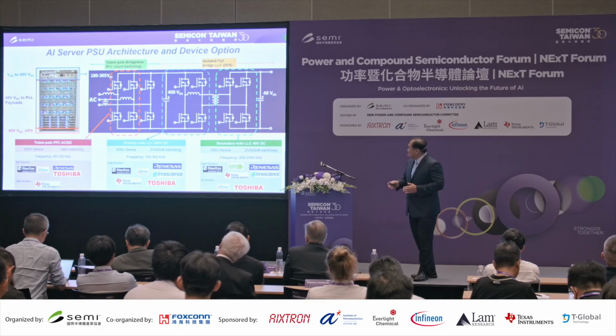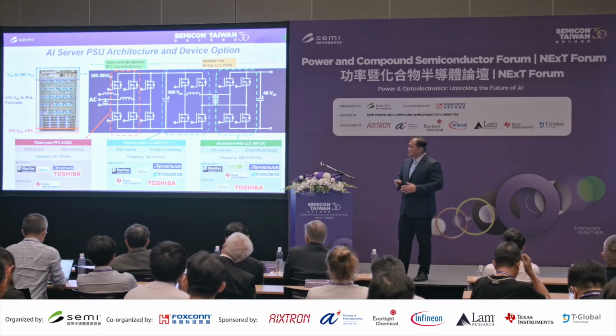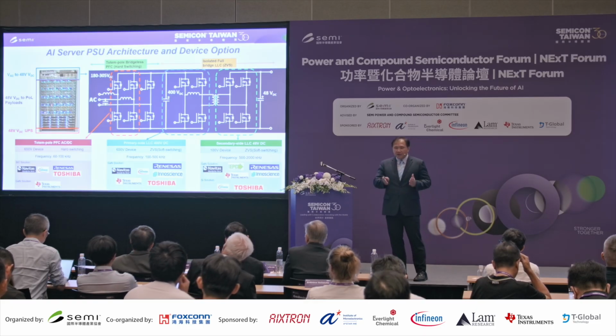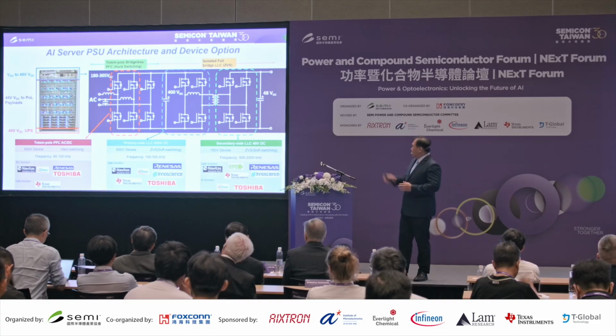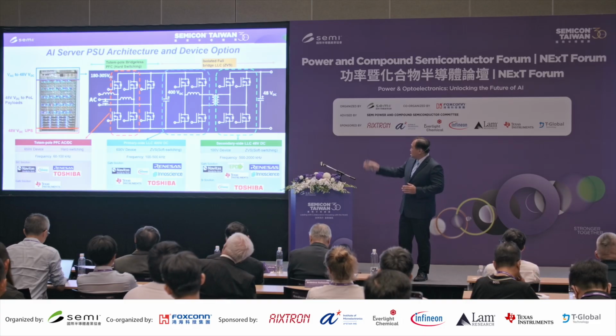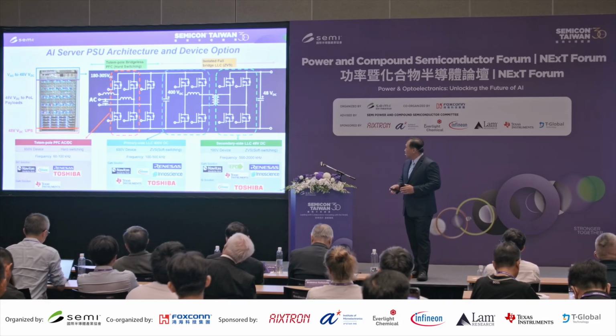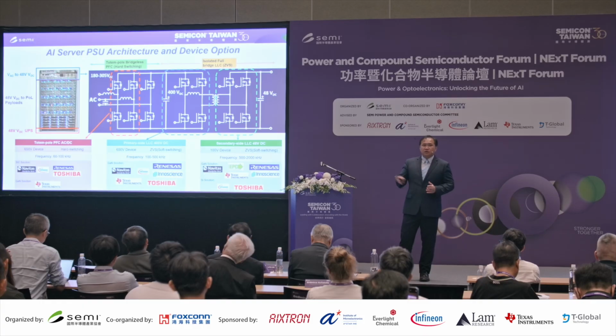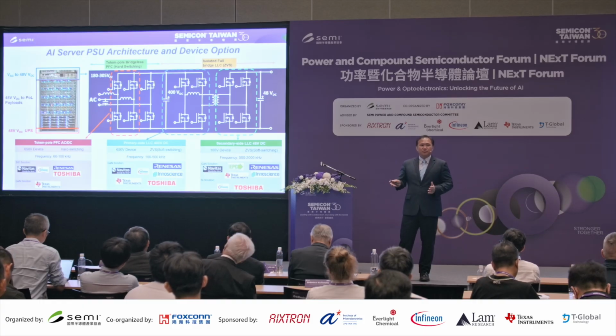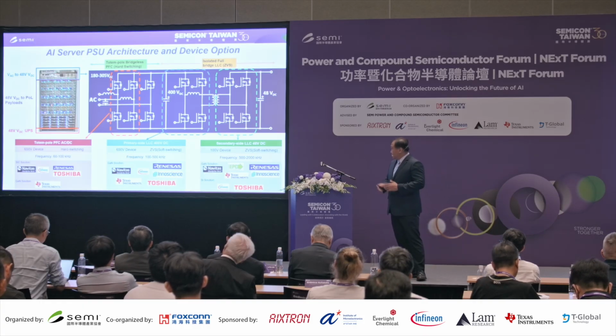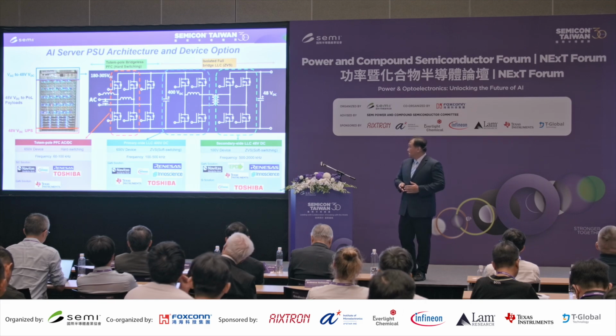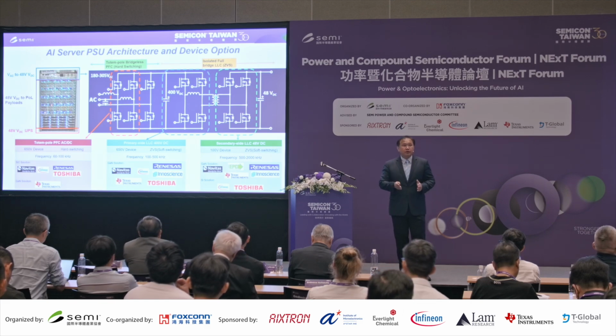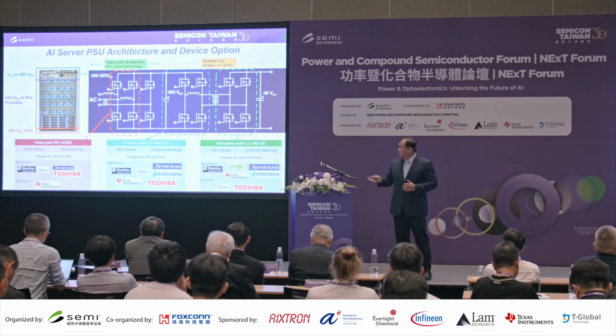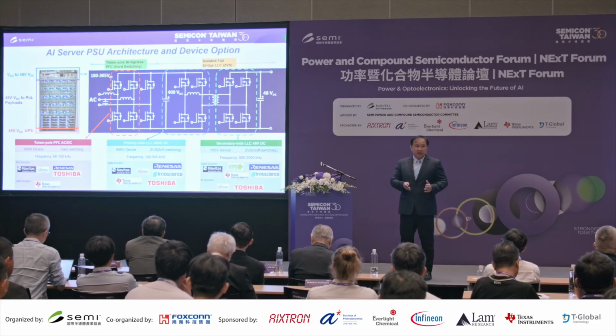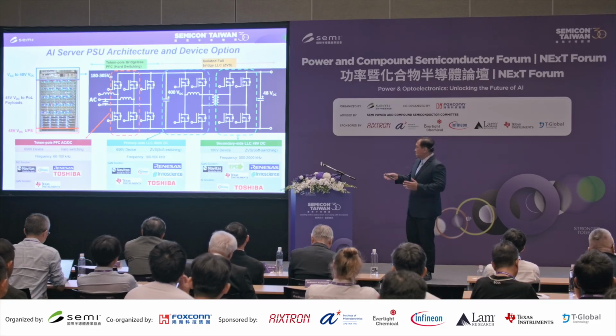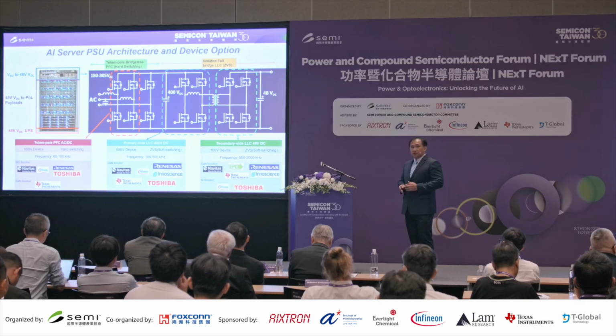For the primary side and the secondary side of the LLC it is very simple, it's soft switching. So gallium nitride can play a very good role for these two applications, no matter the 650 volt and the 100 volt. Okay, but this is not the case for the AC to DC hard switching. Why? Because you may know Navitas and Infineon both have a very good gallium nitride solution, but eventually they still use GeneSiC and CoolSiC to be the first AC to DC converter device.